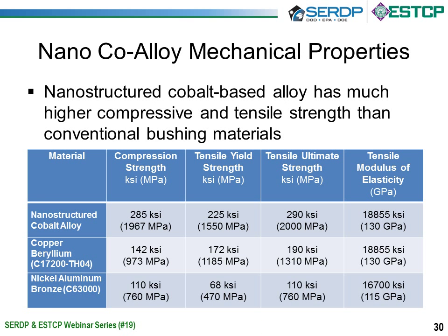Here's a table that shows some of the mechanical properties of the cobalt alloy compared to copper beryllium and another standard bushing material, which is nickel aluminum bronze. So you can see in compression strength, the nanostructured cobalt alloy has higher strength than the copper beryllium and the nickel aluminum bronze, and higher tensile strength. The modulus of elasticity isn't generally changed by the nanostructure, and it's actually the same as the copper beryllium.